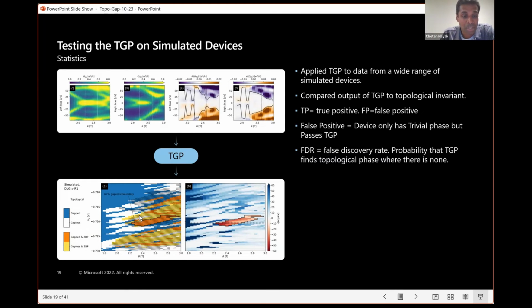Okay. Then on top of that, there are some regions like this yellow region here, where there are stable zero bias peaks, but it's not topological, or not yet. And that's just because it's an inhomogeneous system, and near the junctions, the potential can be different than in the middle of the wire. And sometimes in the junctions, you go into the topological phase first, and then later you go into the topological phase in the bulk of the wire. I see.